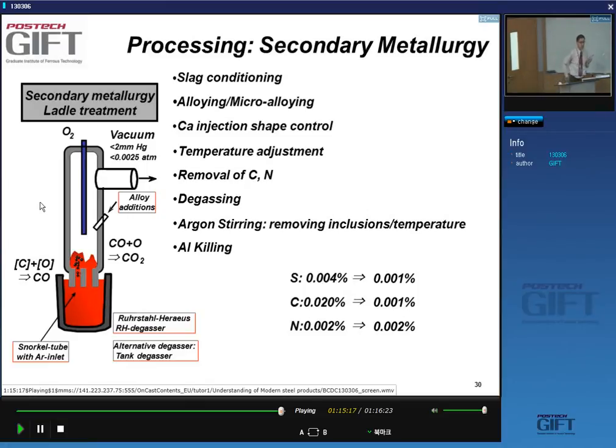Most of the degassers, we call this degassing. Actually, the reason is because you remove the carbon in solution and the oxygen in solution as CO, yes? You call it a degasser. We call it RH degasser. RH stands for Ruhrstahl Heraeus, the inventing companies of this process. It's universally used, yes? And there is an alternative which costs less but is not as effective, the tank degasser.